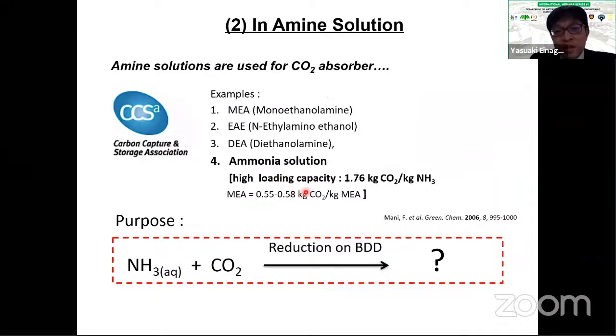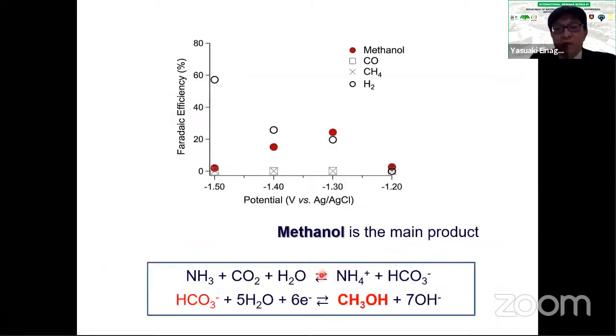Okay. Another direction is amine solution. Amine is very important for the carbon capture system. The CO2 is absorbed in this solution. To check this property, we use ammonia, and in ammonia, carbon dioxide is dissolved. Then what happened by the reduction of this amine solution, an ammonia solution? Surprisingly, methanol is produced. So this is an interesting topic.